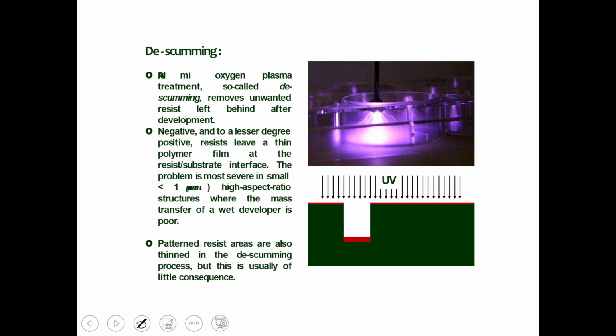Negative and, to a lesser degree, positive resist leave a thin polymer film at the resist-substrate interface. The problem is more serious in the case where the thickness of the photoresist is less than 1 micrometer, where the mass transfer of the wet developer is very poor. In that case, we use oxygen plasma. Patterned resist areas are also thinned in the descumming process, but this is usually of little consequence. So the side effect of oxygen plasma will be very small, so we can use it in that case.